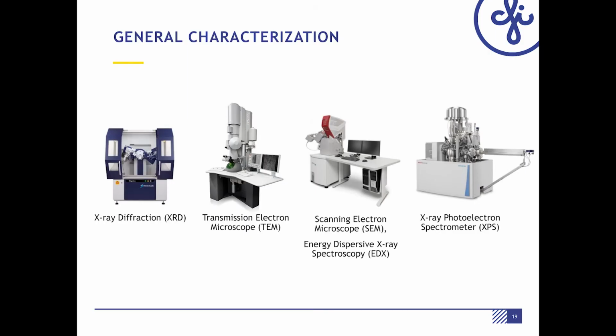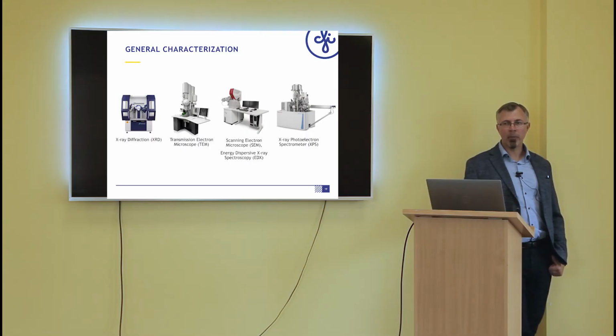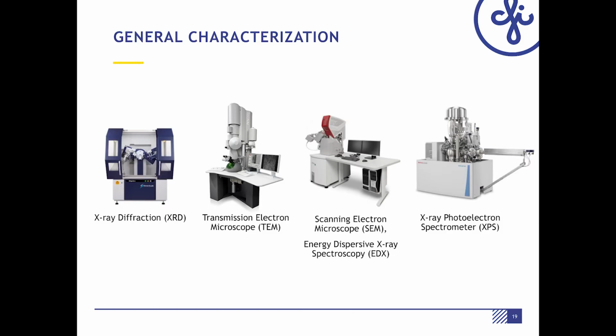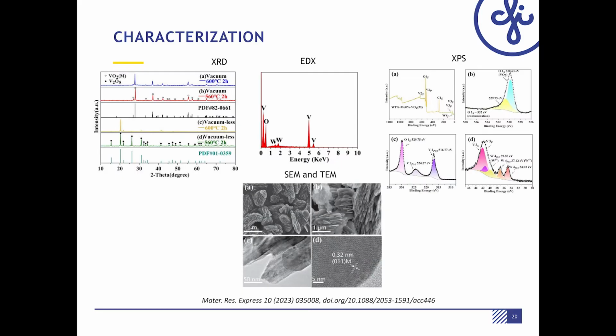After vanadium dioxide coating is deposited on substrate, we can use several methods to characterize its structure and morphology. That is X-ray diffraction, transmission electron microscopy, and scanning electron microscopy equipped with energy dispersive X-ray spectroscopy, or EDX, and X-ray photoelectron spectroscopy. I use this article as a demonstration of application of these methods.